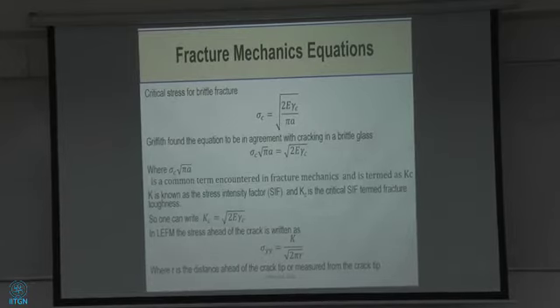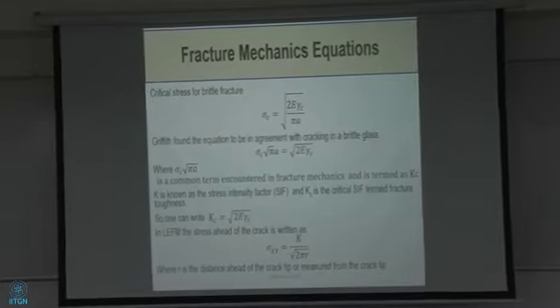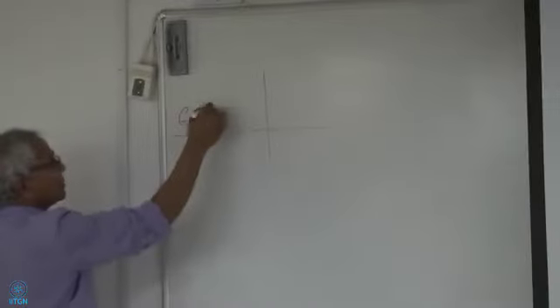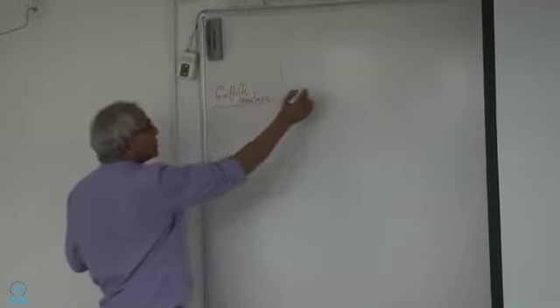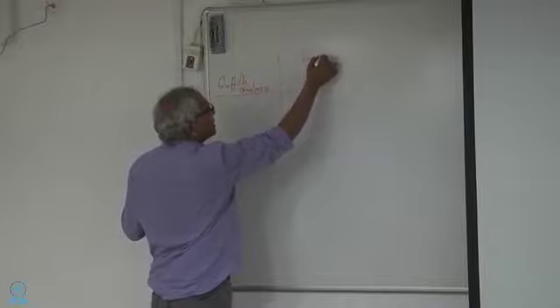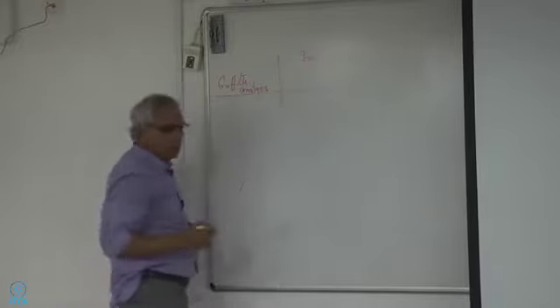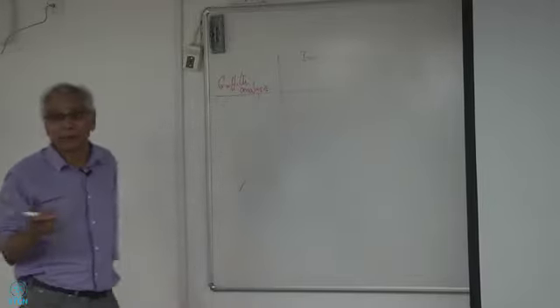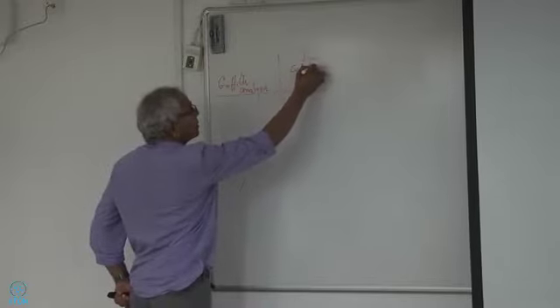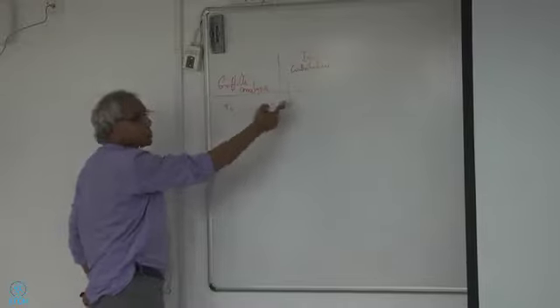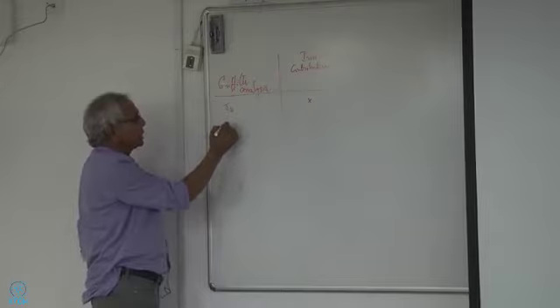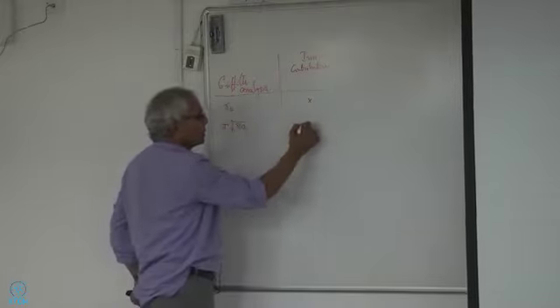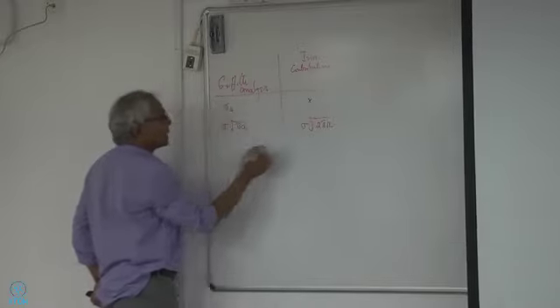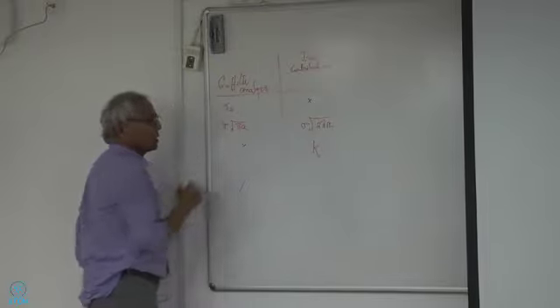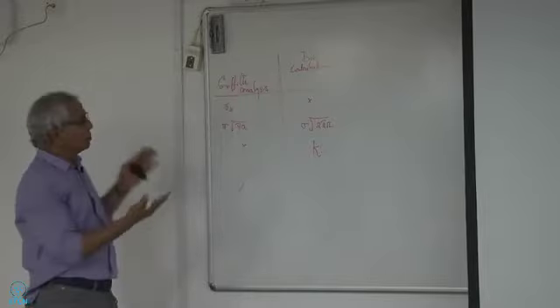Can everybody see this? I know this thing is coming in between. So there is my Griffith analysis. And there is Irwin's, whatever, collection of thoughts. Yeah, Irwin's contributions. So here you have the surface energy, which is not there here, right? But we do have a sigma square root of pi A. We do have a sigma square root of 2 pi R. And there is no K here yet. There is a K here, and then there's no K there. But the similarities are there.